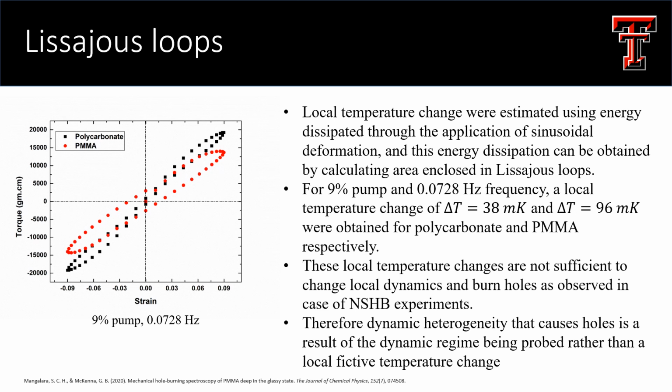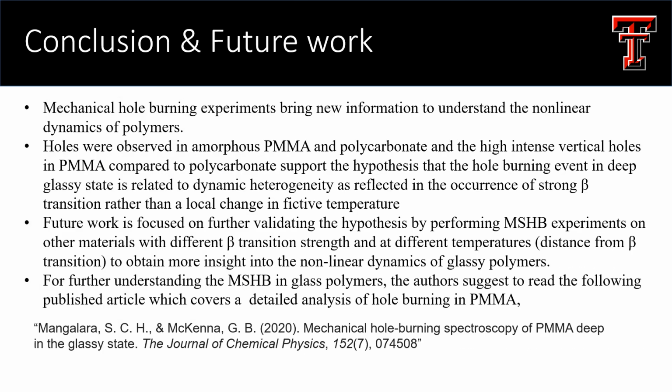These local temperature changes are not sufficient to change local dynamics and burn holes as observed in the case of NSHB experiments. Therefore, the dynamic heterogeneity that causes holes is a result of the dynamic regime being probed rather than a local fictive temperature change. The conclusions and the future work are presented.